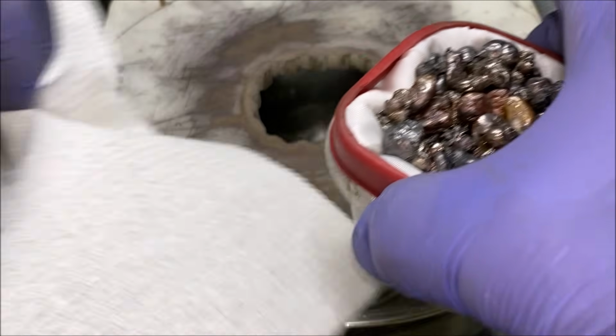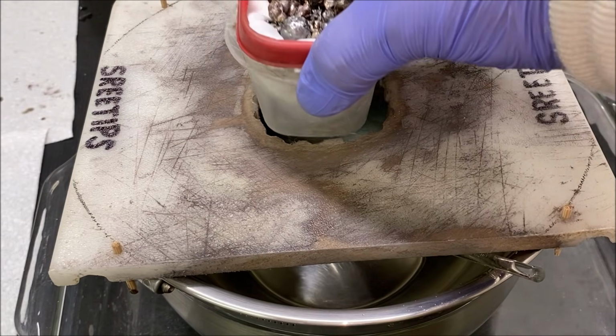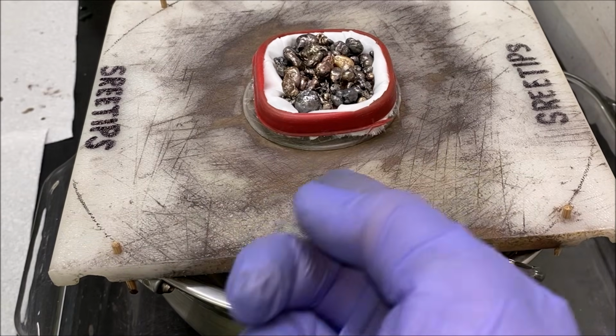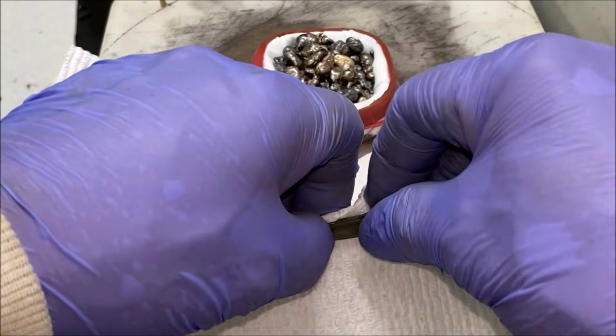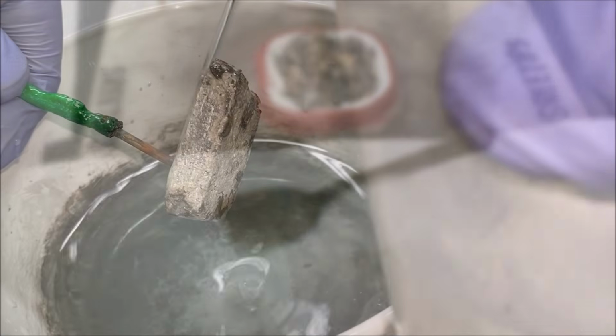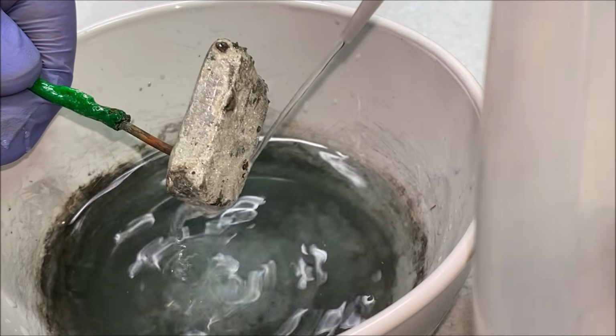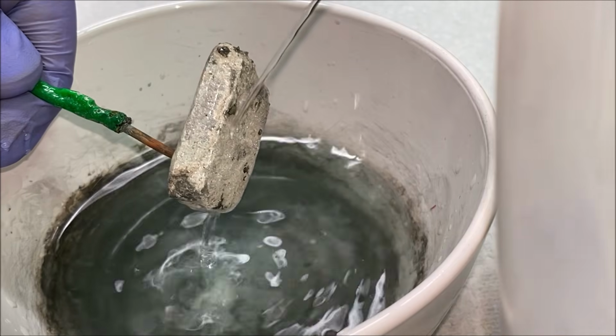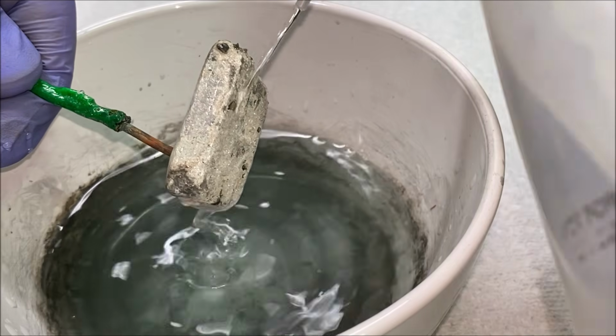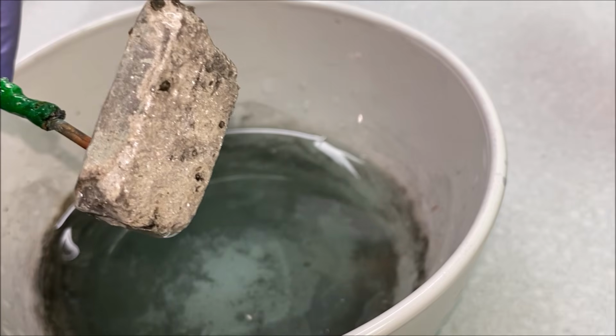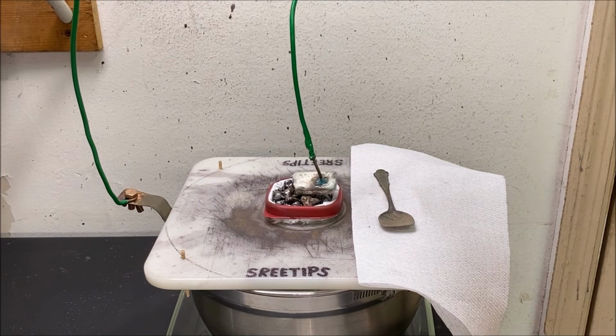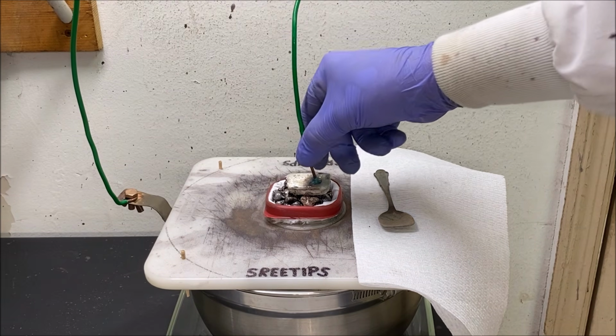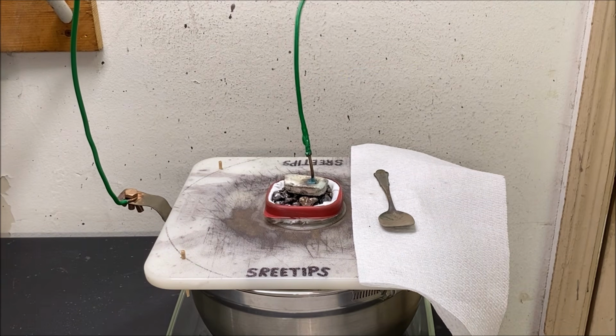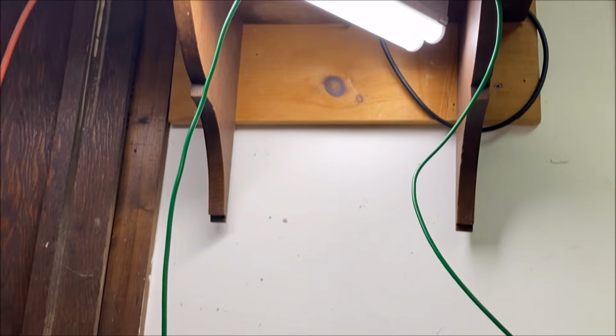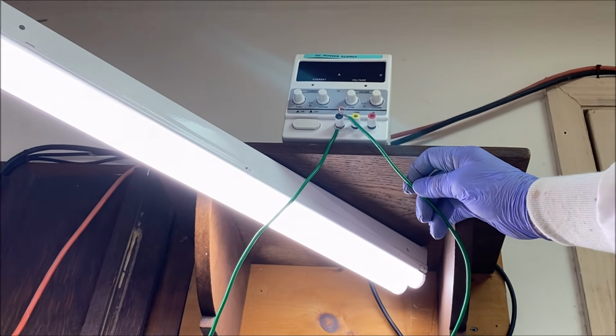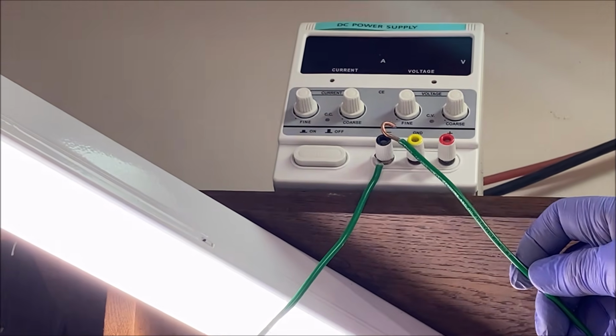Here's our impure silver in our anode filter basket. Drop that in, and the bottom of that will be suspended in the electrolyte in our cell. This is the anode bar, and I rinsed it with some distilled water to get all the slimes off from the previous silver cell run, so we've got a nice clean contact surface. Here we go. We're going to put the anode electrode bar on top of our impure silver in here, and up here what we'll do is make the connection to the positive side of the power supply.